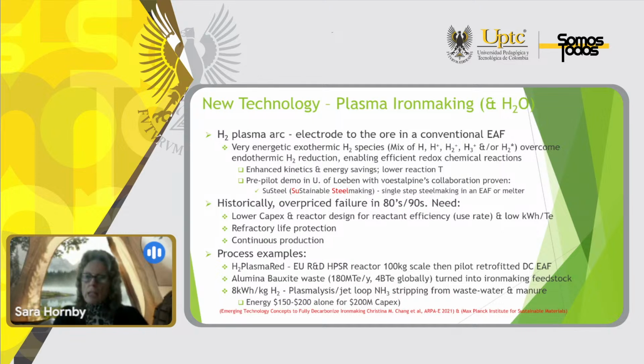And there is a pre-pilot demonstration at the University of Leoben with voestalpine collaborating with them, called SuSteel. It's a single-step steelmaking process in an electric arc furnace or a melter. As I said, historically overpriced. We need to find lower capex and better reactor design for efficiency and low kilowatt hours per ton requirement, which was also a problem before. The refractory life needs to be improved, and the ability to continuously produce needs to be designed.